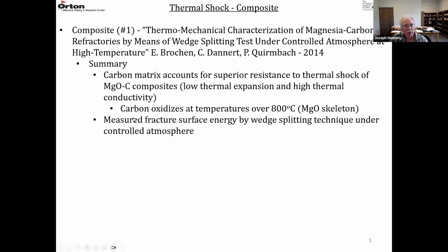The problem with these carbon matrix composites is carbon oxidizes at high temperature. Usually it starts oxidizing at 600. By the time it hits 800 degrees C, the oxidation is pretty extensive, and you end up removing the carbon and you end up with an MgO skeleton. So they're great in thermal shock and corrosion resistance, as long as you keep the oxygen or CO2 away from the carbon. In this work, they measured the fracture surface energy by wedge splitting under a controlled atmosphere at elevated temperatures.